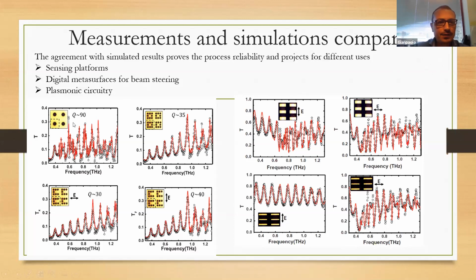We can see here, in the first very simple metagrid made of periodic holes, we have achieved maybe the highest quality factor in resonance in the terahertz regime, almost 90, and also dichroic metasurfaces, where we can tune the enhancement of transmission just according to the polarization of the impinging wavelengths. On the right, we see 4 examples of dichroic metasurfaces made of tiny resonators in different shapes. It's very interesting in these 2 slides. Of course, the change of polarization provides a really large change in the transmission, and this is very good for several technological applications and sensing as well.